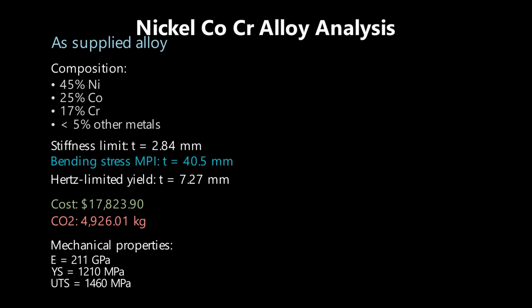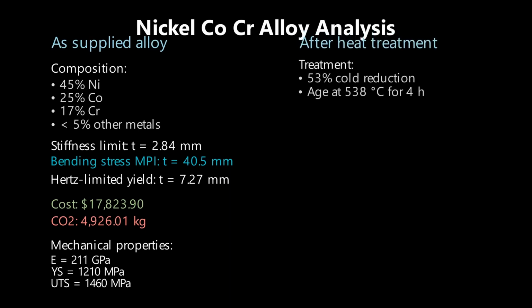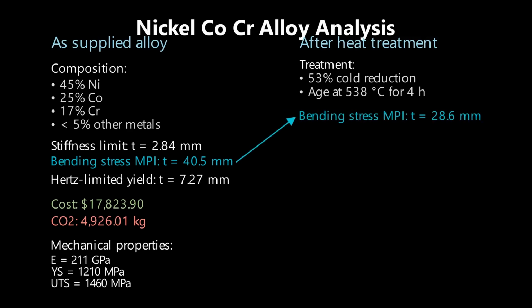Taking the maximum value of 40.5 mm, we calculated the cost to be $17,823.9 and a CO2 output of around 4,926.01 kilograms. The best heat treatment for this nickel alloy to maximize strength was found to be 53% cold reduction, then aging it at 538 degrees Celsius for 4 hours.